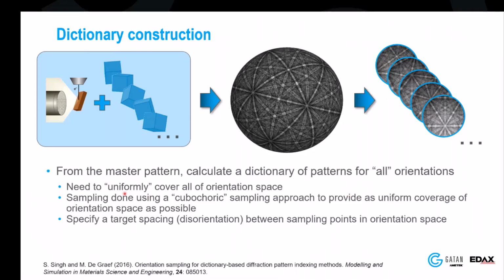So when you're actually building this, you want to make sure you're getting uniform information across the entirety of orientation space. You'd have to build these libraries targeting a specific step size. Dictionaries are discrete in their construction, so if I wanted to make something every, let's say, half a degree, I would have to do it every half a degree in the full orientation space. And those could be quite large, especially for lower symmetry materials. There are big fancy words up there like cubochoric, which really talk about this.